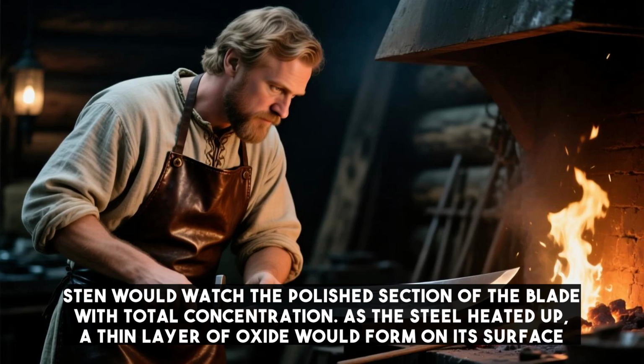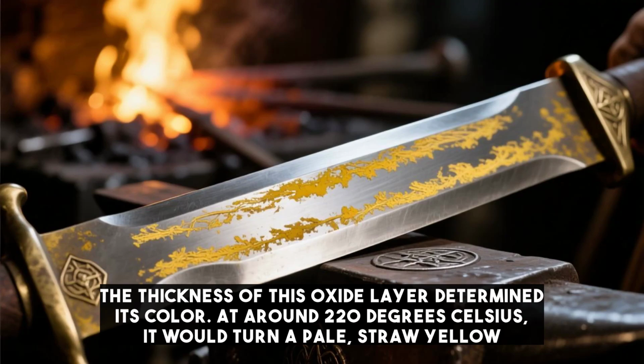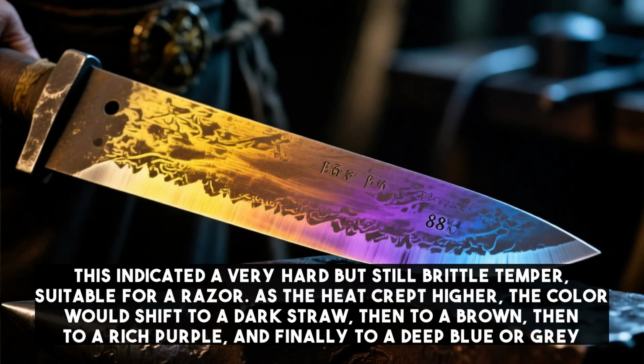Sten would watch the polished section of the blade with total concentration. As the steel heated up, a thin layer of oxide would form on its surface. The thickness of this oxide layer determined its color. At around 220 degrees Celsius, it would turn a pale straw yellow. This indicated a very hard but still brittle temper, suitable for a razor.